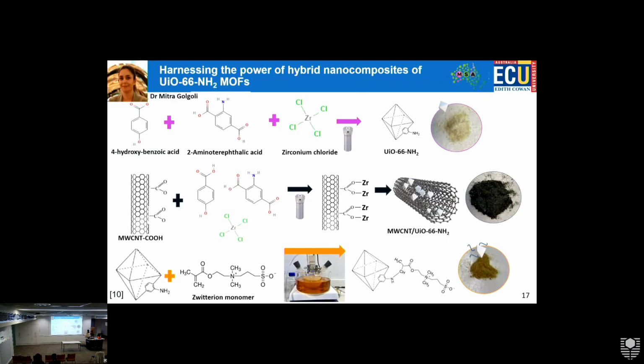So another study by Mitra. In here, she used UiO66-NH2 MOFs. These are zirconium-based MOFs. Zirconium is less toxic than cobalt, chromium, and other types of materials that are being used for MOFs. This MOF is highly water stable compared to the other MOFs. Many of the MOFs have a water stability issue, so when they encounter water, they degrade. Basically, if they degrade, they will reduce the efficiency of the membranes.